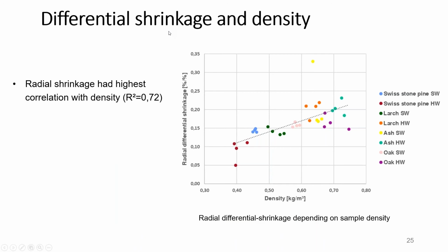Actually, I'm about to finalize the examples I'm presenting to you. There's one other student who worked on the DVS and wood and structural issues. And this is a graph that wood scientists know is the case. He picked up from the small samples the differential shrinkage, so the shrinkage rate per percentage of moisture change, which is called differential shrinkage. You also did the swelling, and later you measure the density of the sample. And of course, the higher density gives you the higher differential shrinkage. That was a DVS created image.